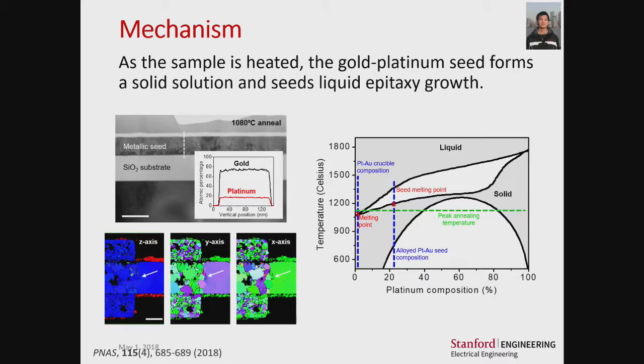We've done further study of the precise mechanism, and if you could just bear with me, I know this isn't a material science seminar, but in essence, what happens as you heat this up is that the gold and platinum diffuse together and form a gold-platinum solid solution. And this solid solution has, as we see on this phase diagram between platinum and gold, a melting point that is higher than the melting point of gold, which is to say right here. So what we have in this case is a solid platinum-gold seed, which serves as a site for epitaxy nucleation as the gold melts and then cools.